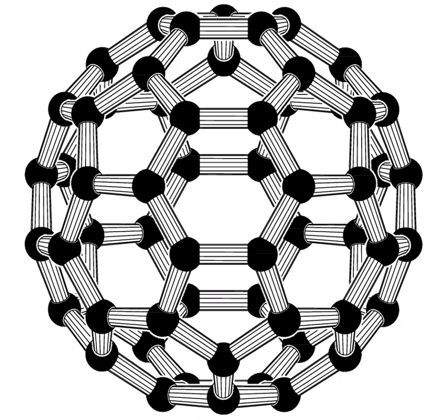Unlike graphene, which is a two-dimensional semimetal, carbon nanotubes are either metallic or semiconducting along the tubular axis. For a given (n,m) nanotube, if n equals m, the nanotube is metallic; if n minus m is a multiple of 3 and n does not equal m and nm does not equal 0, then the nanotube is quasi-metallic with a very small band gap, otherwise the nanotube is a moderate semiconductor. Thus, all armchair (n=m) nanotubes are metallic, and nanotubes (6,4), (9,1), etc. are semiconducting.